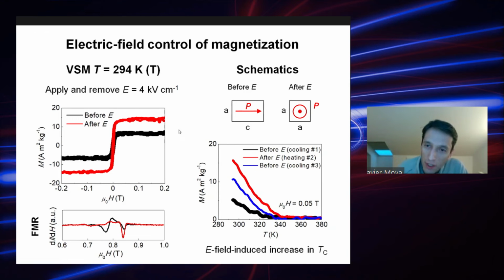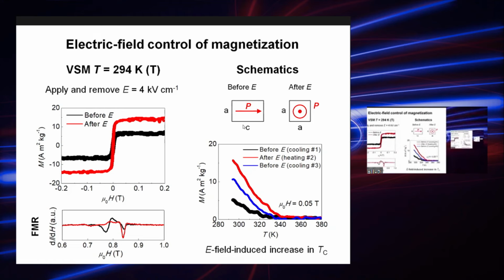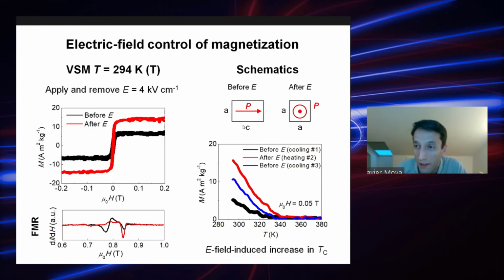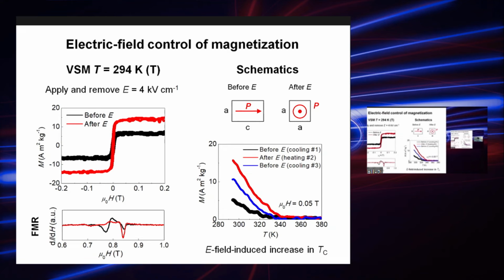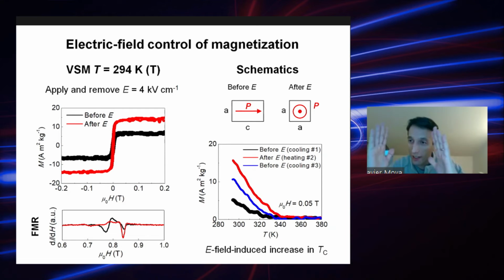And when this happens, the strain that the substrate is showing to the film is very large. Because the lattice parameter of LSMO is around 3.86, and the lattice parameter, let's say the C-axis lattice parameter for our substrate is 4.02. So this is a very big change in strain. And when this happens, because the LSMO is so strained, basically you are changing the distance between the manganese atoms.